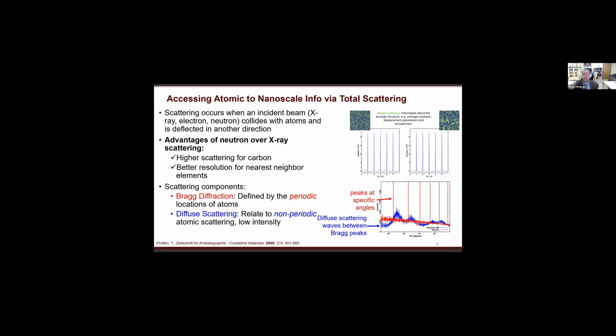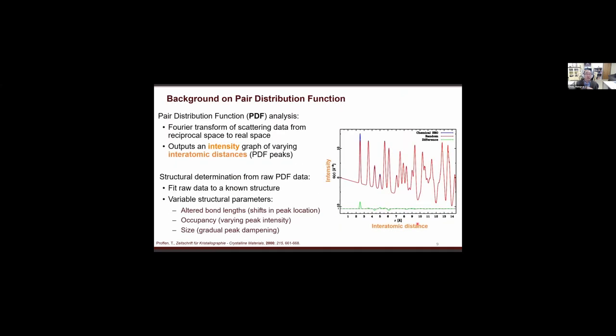Okay, how should we do this? Let's use some of the examples we have. First, I'm preaching to the choir here, but let me talk a little bit about the pair distribution function. Pair distribution function analysis is the Fourier transform of scattering data from reciprocal space to real space, and it outputs an intensity graph of varying interatomic distances, or PDF peaks. So here are the interatomic distances, and here is the intensity.